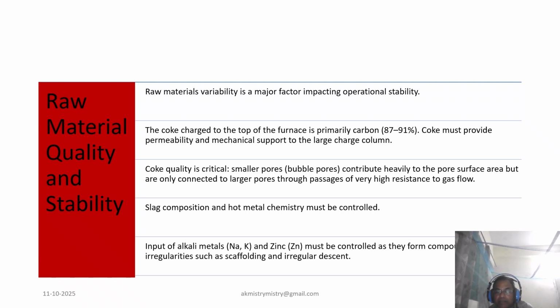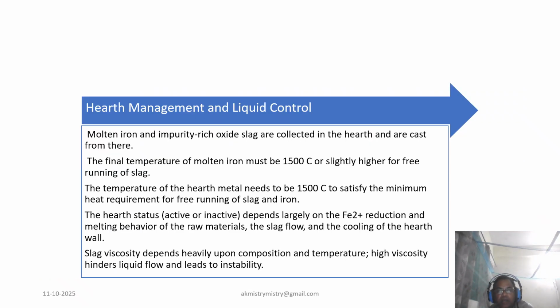Now, the hearth, where the final product accumulates in the form of molten iron and slag, is collected. To ensure the liquids are free running, the final iron temperature must be kept slightly above 1500. Crucially, any accumulation of liquid in the hearth creates back pressure on the raceway. This back pressure is a major driver of the irregular burden descent. Therefore, keeping the hearth thermal system steady is paramount for overall stability.